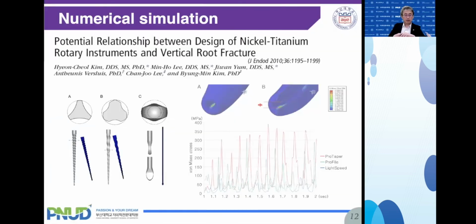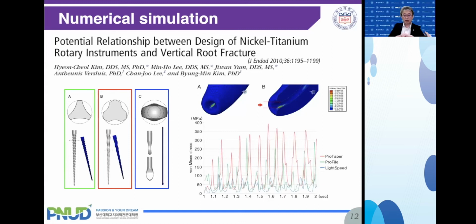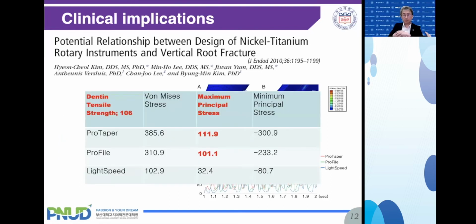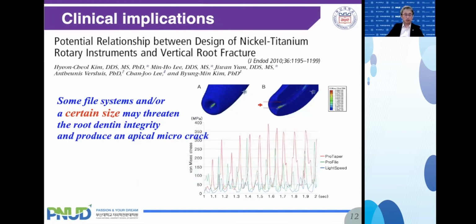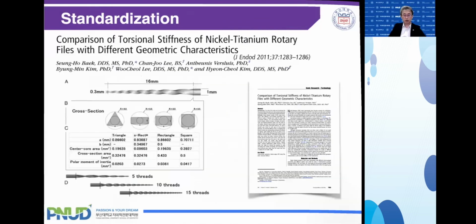In this study, we compared the ProTaper and ProFile. As you guessed, the steeper taper of ProTaper shows a higher stress on the apical root dentin. Under the condition of this study, the apical stress by ProTaper and also ProFile were almost similar to the dentin's tensile strength. You can see the number values, 100 something, and the dentin's tensile strength is 106. So we would say that some file systems or a certain size of file may threaten the root dentin integrity and may produce apical microcracks. So we have to take care when we select the proper instrument.